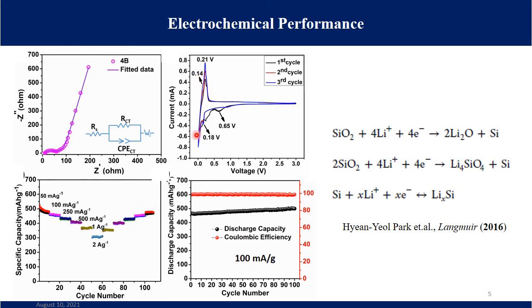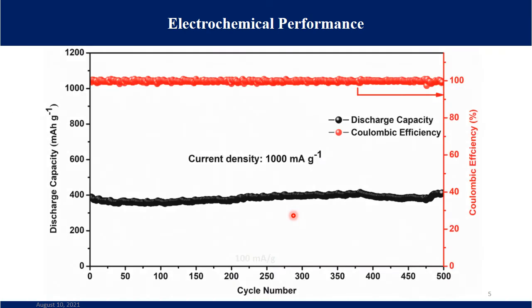which is LiC6. The cell shows a high discharge capacity of 501 milliamp hour per gram with 98.4% coulombic efficiency even after 100 cycles of charge discharge. Furthermore, at high current densities like 1 ampere per gram, the cell delivers an initial capacity around 390 milliamp hour per gram with a 99.2% coulombic efficiency. Even after 500 cycles, the cell delivers an outstanding capacity around 411 milliamp hour per gram with 99.4% coulombic efficiency.